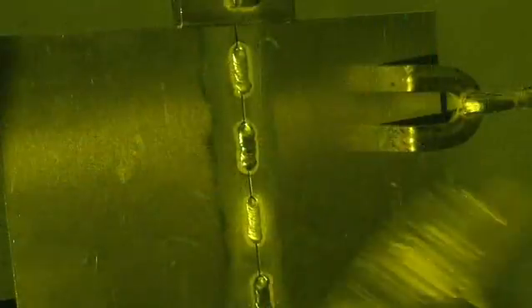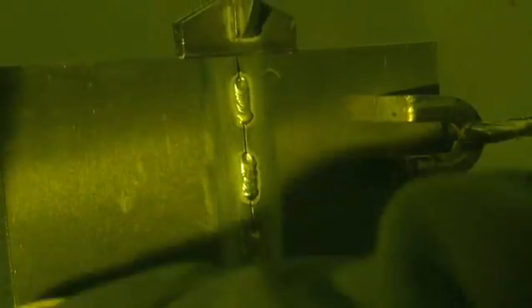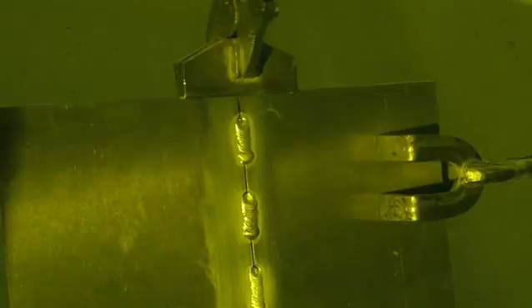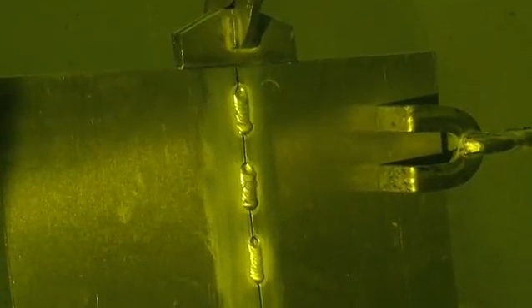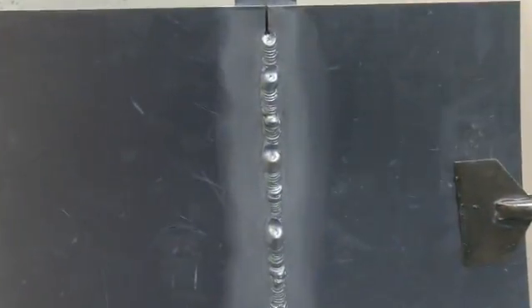Another welding technique that can be used on aluminum is the skip technique. The skip technique uses multiple welds randomly staggered along the seam to help control heat. When working with skip welds, it is critical to use a wire brush on the joint between welds. If contaminants and soot are not removed, a weld will have porosity and may have poor penetration. As more welds are added, a continuous-looking weld seam begins to appear.